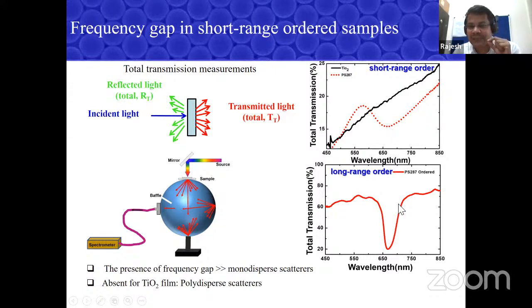And if you look at a sample with the same scatterer, same material, made as a long range ordered sample, which is a photonic crystal, it exactly showed the transmission dip close to 650 nanometer. So we claim that our sample, because of the short range order, has Bragg-like scattering and will give a resonant frequency gap. So this is what we call a frequency gap in short range ordered systems.